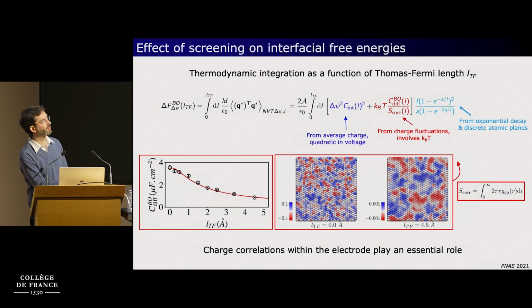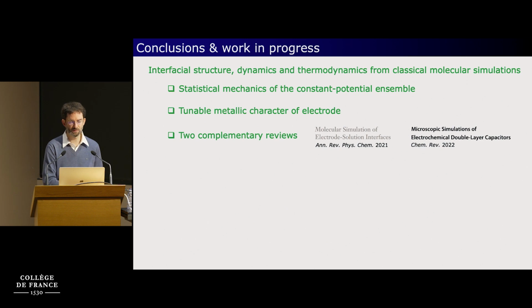And there is a last term in the model which comes from the decay of the potential as you go deeper and deeper into the solid. This involves the exponential decay and the fact that you have discrete atom planes that are separated by some characteristic length A, which is related to the lattice of the metal. And all this work shows that charge correlations within the electrode play an essential role in the interfacial thermodynamics.